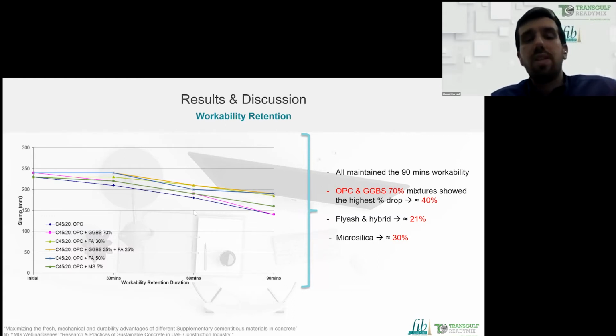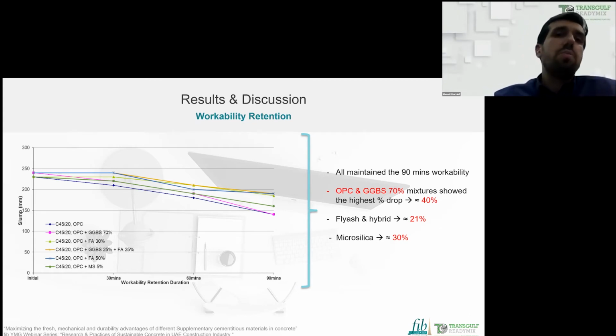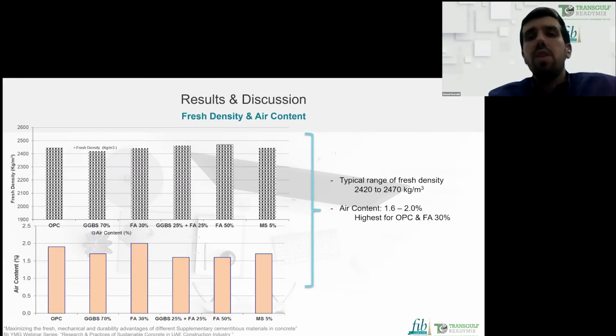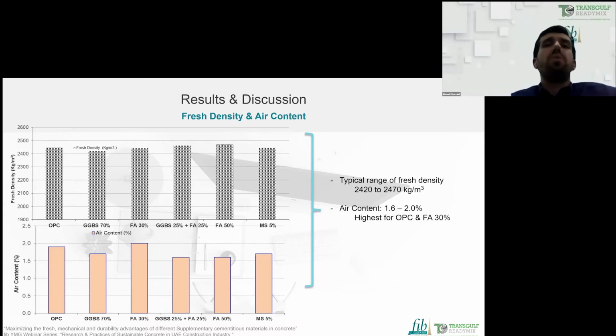You can see the drop is gradual, but as an observation, the drop was the highest for the GGBS mix. From an initial 230 to after 90 minutes, it dropped around 40%. However, we are talking here about around 230 to 140 slump for the GGBS. For fresh density and air content, all of them showed a similar typical fresh density and typical air content between 1% and 2%.